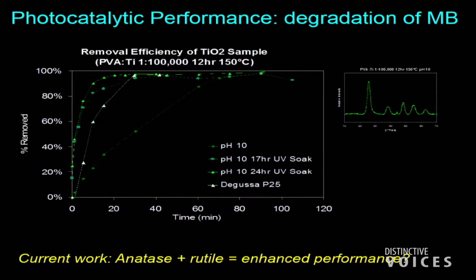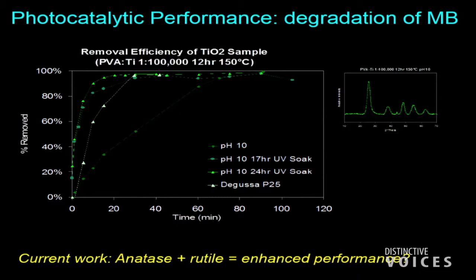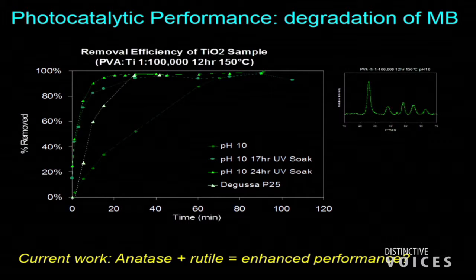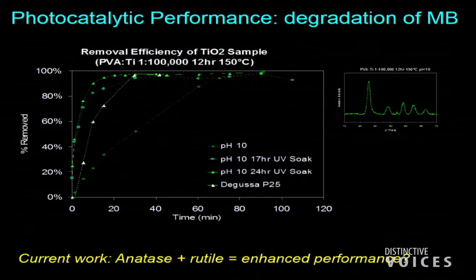And so we've tested these materials. This is a plot where I've taken a certain organic contaminant, and I put it in our water with our titanium dioxide catalyst, and we put light on it. And we measured how fast it can degrade our organic contaminant. So 100% is the organic is gone. So we compared an industrial photocatalyst. This company makes this catalyst.